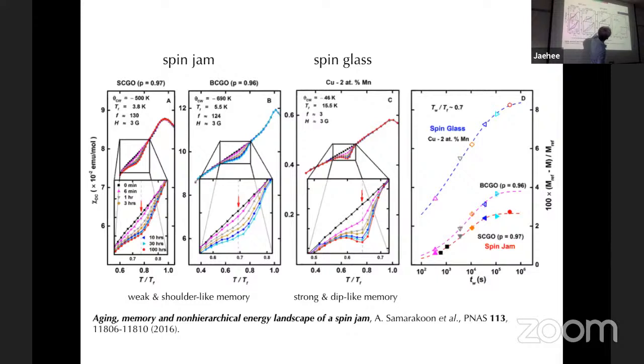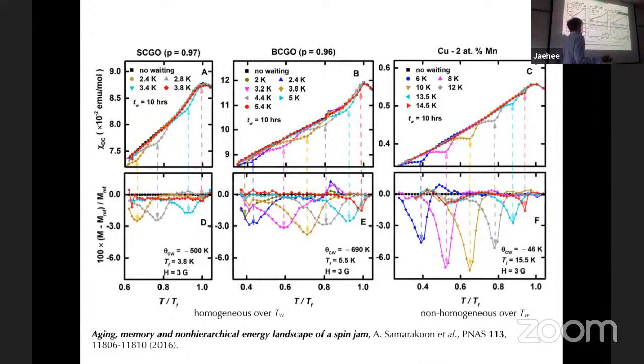Another one is this aging, the amount of aging. So the spin glass case ages faster than spin jam, right? So how much did it age? We plot it as a function of waiting time. Then this spin jam case ages slowly, and the other, spin glass, ages quickly. So there are two things: quick aging, faster in spin glass, and spin jam just ages slowly. Another one is the dip appears in the spin glass, but only a shoulder appears in spin jam.